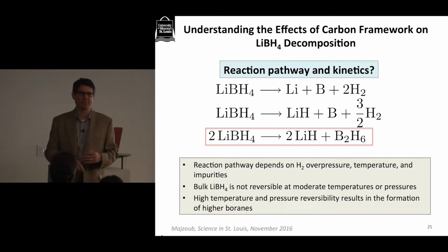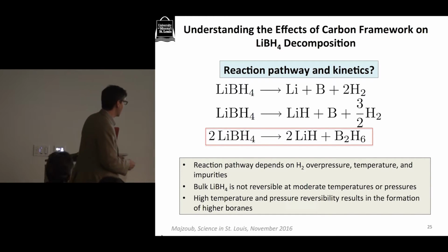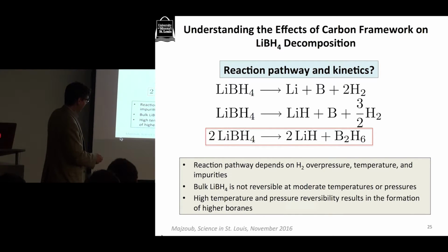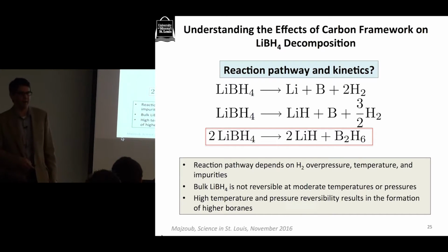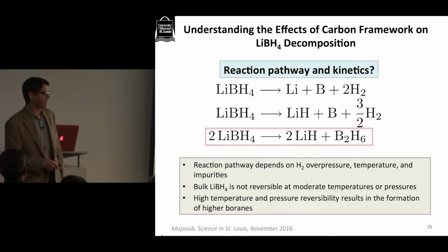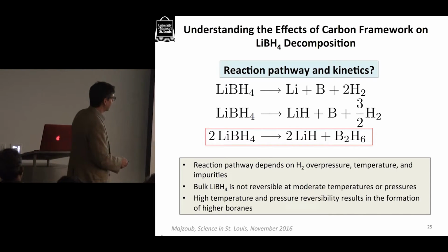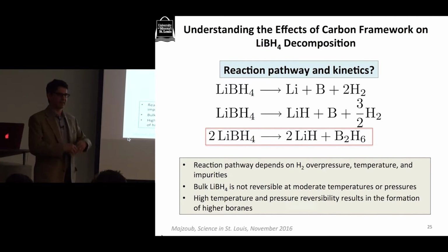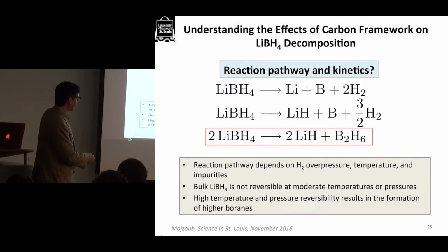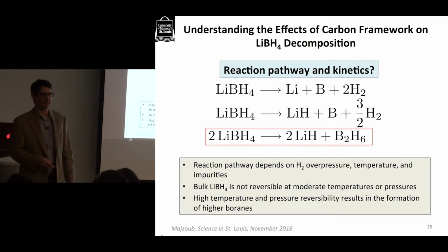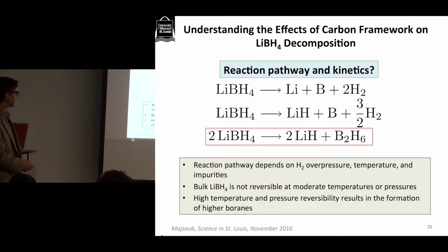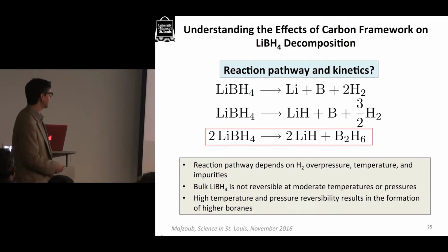And in particular, in bulk, one of the reaction pathways that we know is followed is that we go from lithium borohydride to lithium hydride, and we get this compound B2H6. This is a compound called diborane, and it also comes off of the material. Unfortunately, diborane is bad for two reasons. One, it's a gas, and if it escapes the system, some of our active material is gone, and so we can't rehydrate it. And the other problem is that diborane is a toxic gas, and so we don't want that to be released at all.